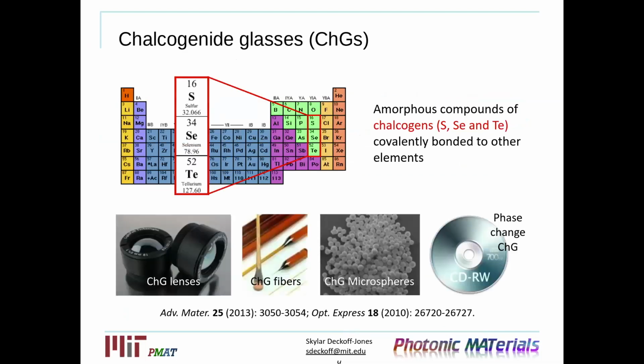And when it comes to the light guiding medium, chalcogenide glasses, which are glasses comprised of the chalcogen atoms, sulfur, selenium, and tellurium, offer a very preferable material system for creating waveguides in the mid-infrared. So the chalcogenide glasses are already quite popular and available commercially in the form of lenses and fibers, and perhaps most famously for rewritable phase change CDs. However, they also show great promise for integration with 2D materials.